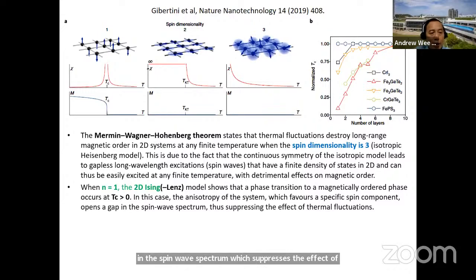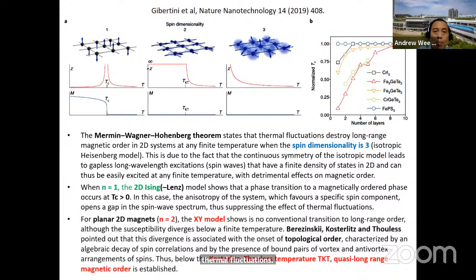And finally, we have planar magnets or the XY model, which shows no conventional transition to long-range order, although the susceptibility diverges below a certain finite temperature. Berezinskii, Kosterlitz, and Thouless pointed out that this divergence is associated with the onset of topological order. And this is a new field which studies systems like these. Essentially, it says that you can get quasi-long-range magnetic order in the XY model below what is known as the TKT, Kosterlitz-Thouless temperature.